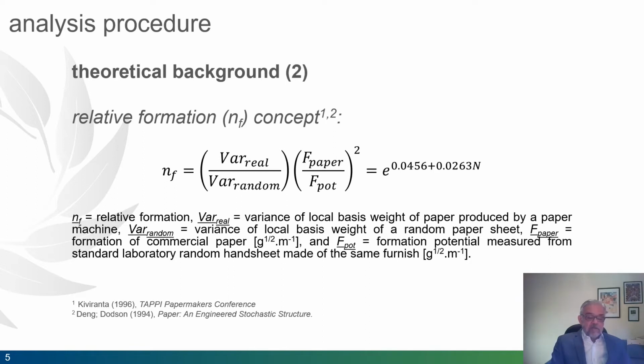The relative formation concept is based on the quantitative ratio between the variance of local base weight of a commercial sheet of paper and the corresponding variance of a random sheet produced from the same furnish, and is given by the relation shown on the screen. So the lower the relative formation index, the better the manufactured paper formation. This expression shows a significant correlation between relative formation and crowding number. That is, the higher the crowding number, the higher the relative formation, or the worse the formation uniformity.